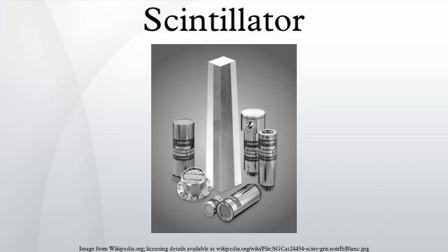Neutrons. Since the neutron is not charged, it does not interact via the Coulomb force and therefore does not ionize the scintillation material. It must first transfer some or all of its energy via the strong force to a charged atomic nucleus. The positively charged nucleus then produces ionization. Fast neutrons primarily rely on the recoil proton in (n,p) reactions. Materials rich in hydrogen, for example plastic scintillators, are therefore best suited for their detection.